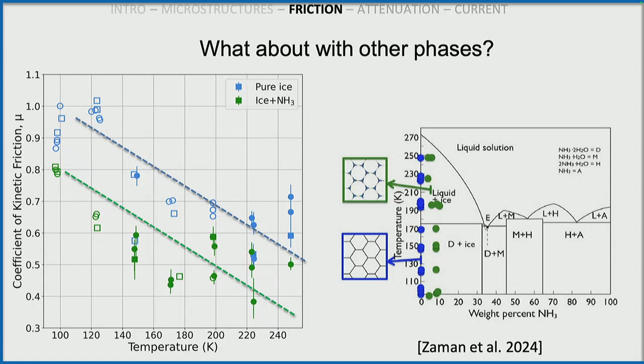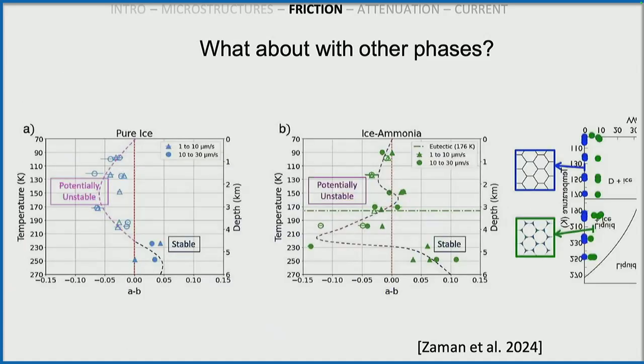So please look at that if you get a chance. But one final thing, how did having the melt phase affect that stability or that seismogenic zone? Well, this is an interesting effect. If you look at this, this is the melting line, and so it's partial melt below this, but solid above this. And the shape of this is almost identical to the pure ice case. But at partial melting temperatures, it seems to go kind of very far extreme in stabilities in both cases.